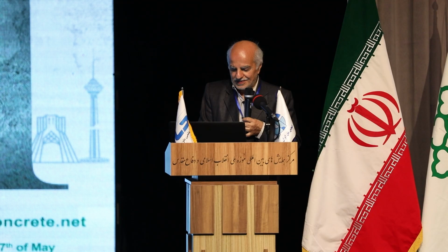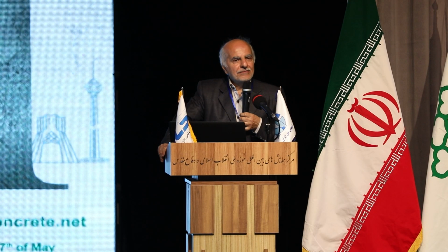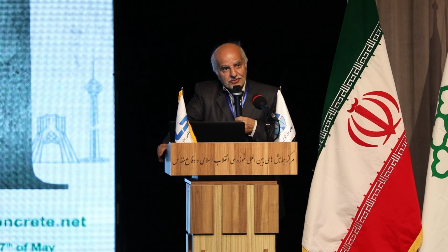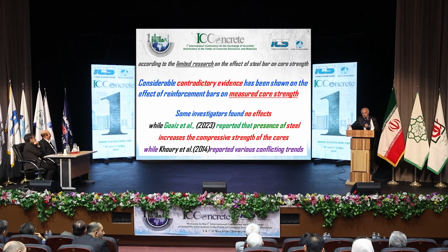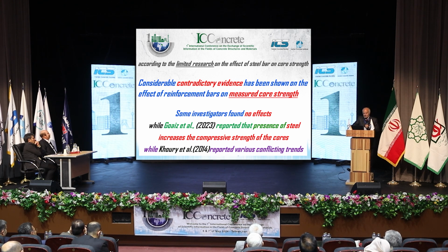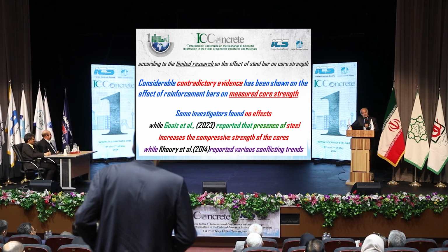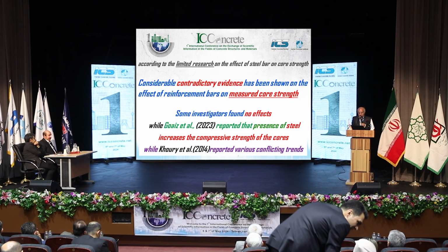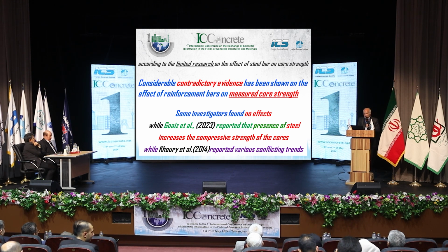Now, let's see the result according to the limited research which has been done by different investigators. Contradictory evidence has been shown on the effect of the reinforcement bar on measurement of core strength. Someone found no effect. Someone like Goaiz reported that the presence of the steel bar in the core will increase strength, and someone like Khoury reported that various conflicting trends will appear.